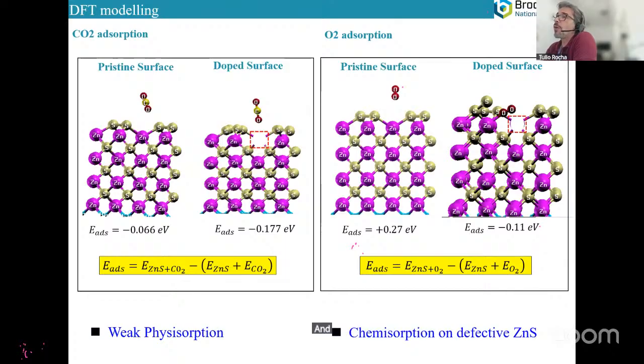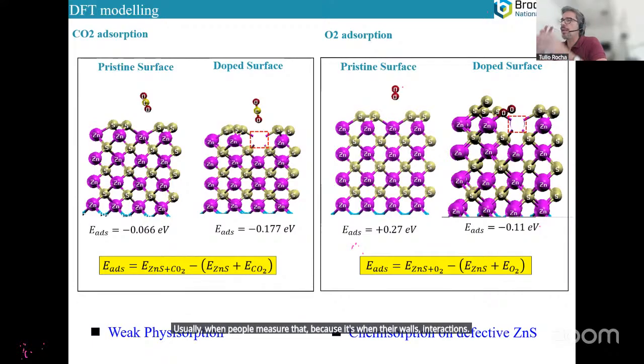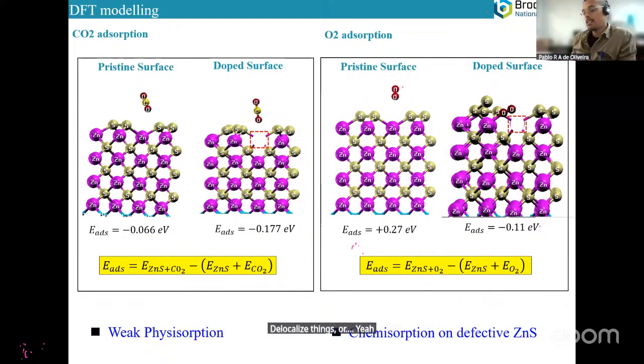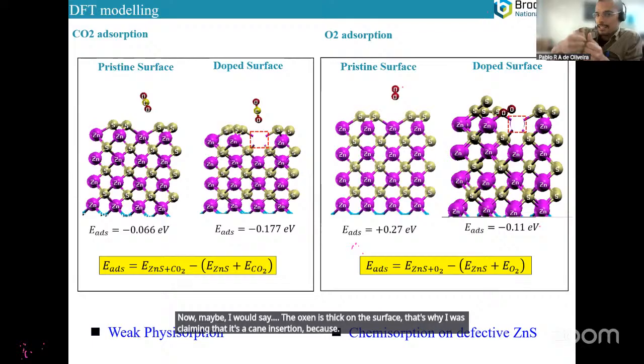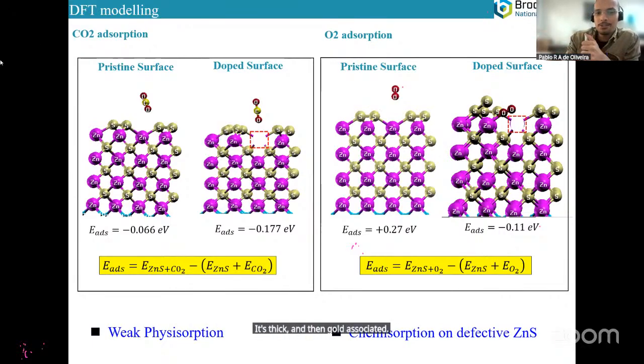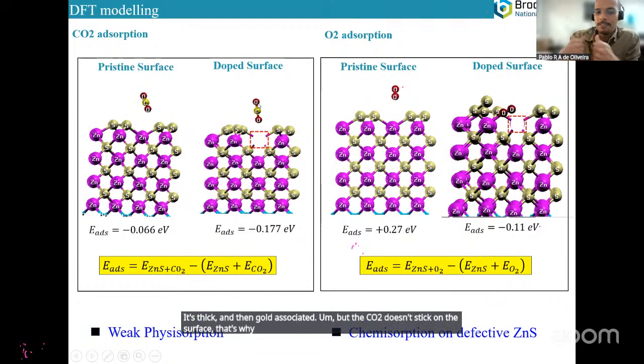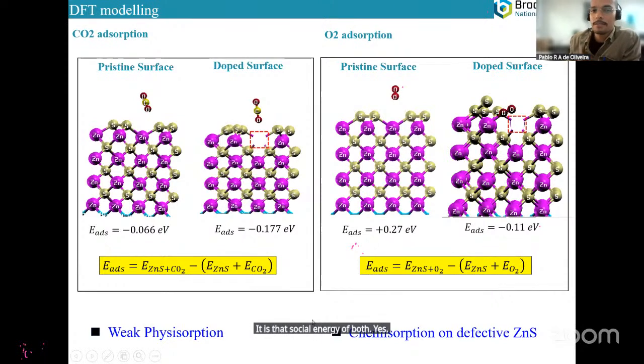And it's almost an order of magnitude difference. Usually when people measure that, it's because it's van der Waals interactions, delocalized things. Yes, I totally agree. But I had to figure out this mechanism; maybe I would say the oxygen sticks on the surface. That's why I was claiming that it is a chemisorption, because it sticks and then goes dissociated. But the CO2 doesn't stick on the surface. That's why I was claiming the physisorption. But I totally agree with you. The first parameter to compare the physisorption or chemisorption mechanism is the adsorption energy of both. Yes, I will correct this for sure.